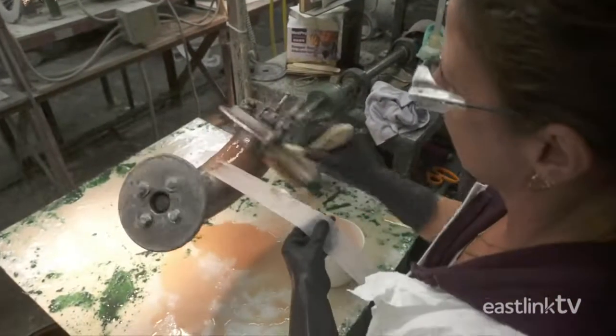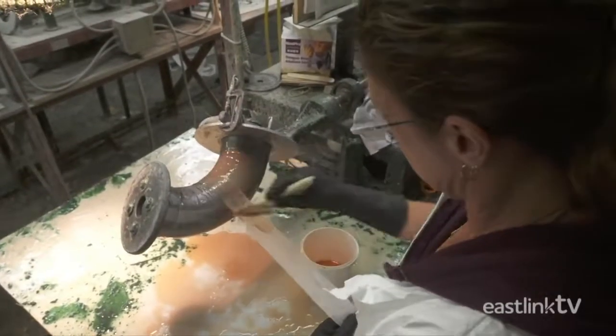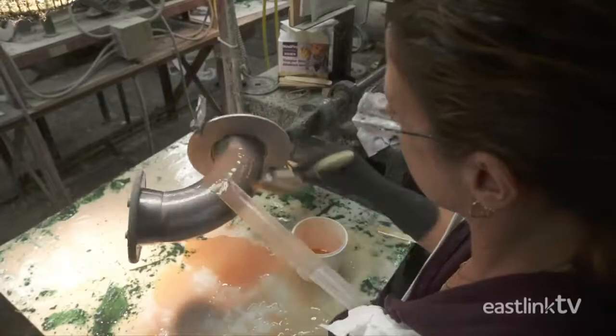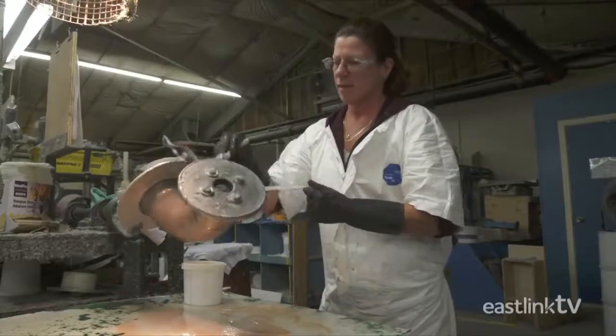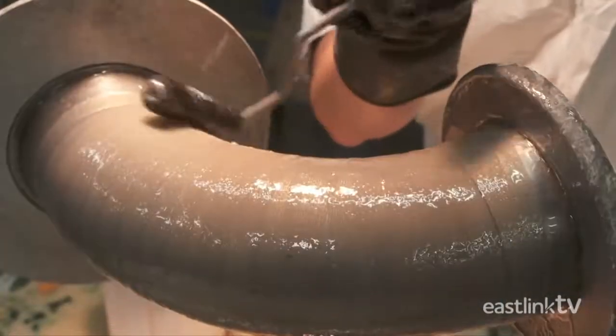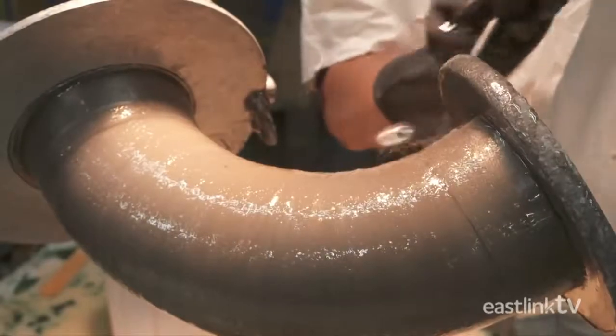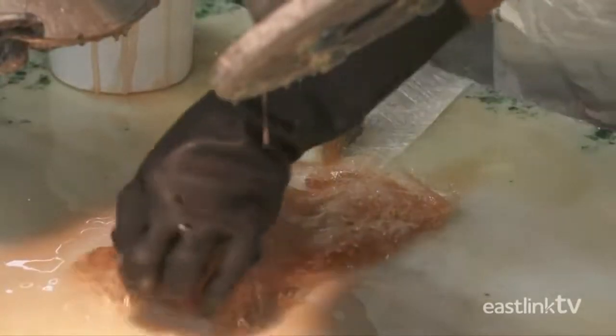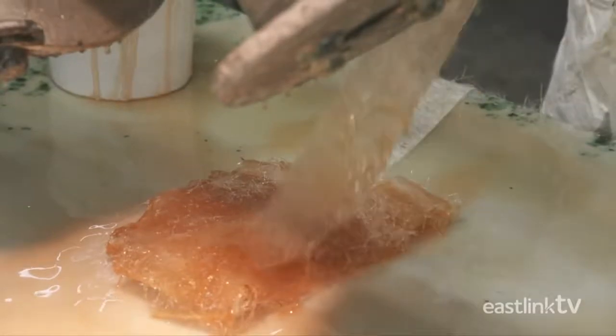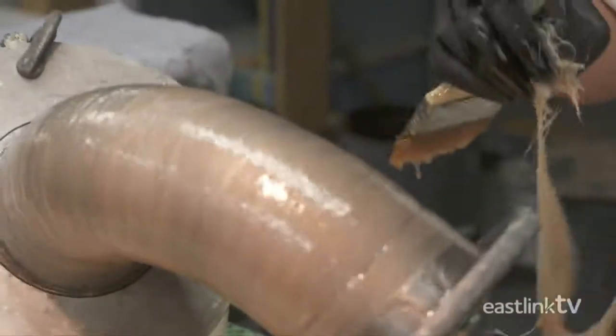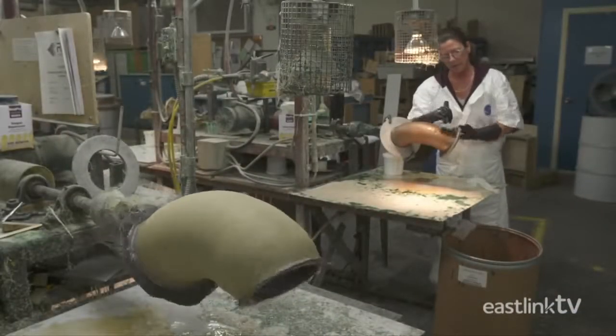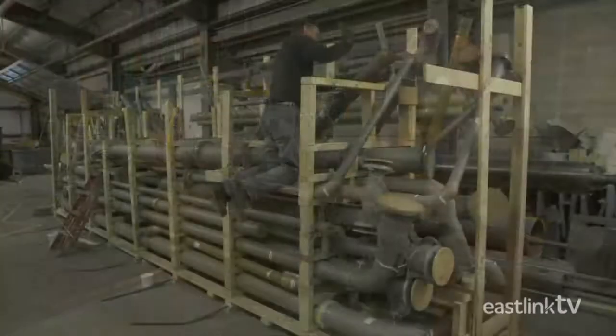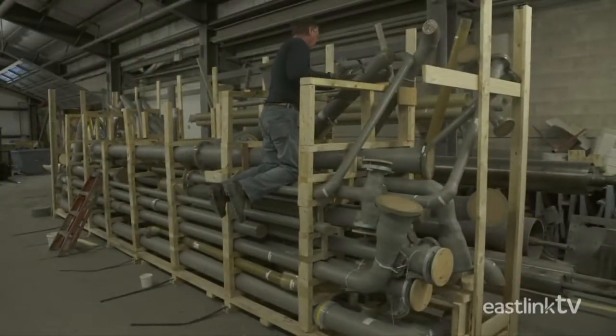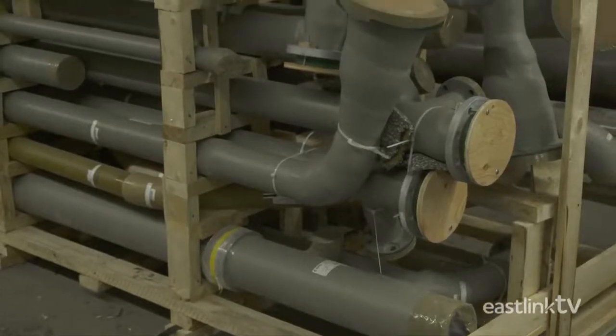Nexus Veil is the first layer of material applied to the mold to start to build up the part, in this case, an elbow. Resin is applied to ensure the Nexus layer is thoroughly soaked. The resin is hand-rolled to remove any air bubbles which would weaken the fitting. The next layer of fiberglass is soaked in resin and applied. Layers of material are added in the same way until the part is fully built up. It cures while turning continuously under a heat lamp for an even finish. At RPS Composites, products are shipped in specialized crates to industrial locations around the world.